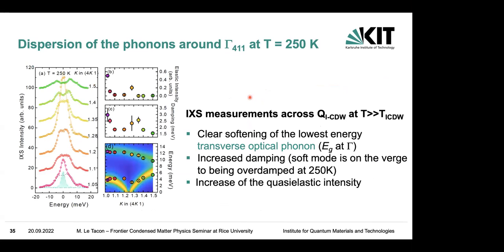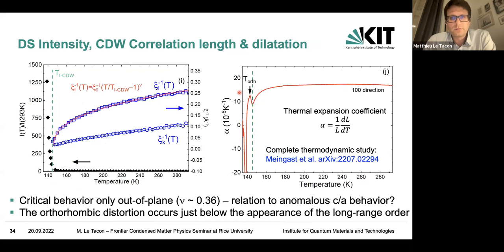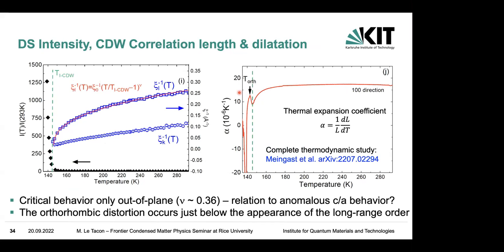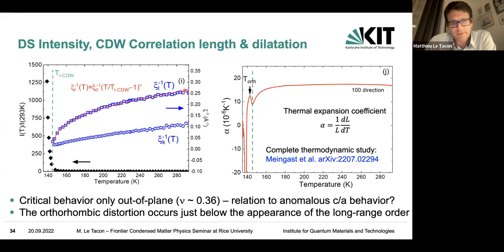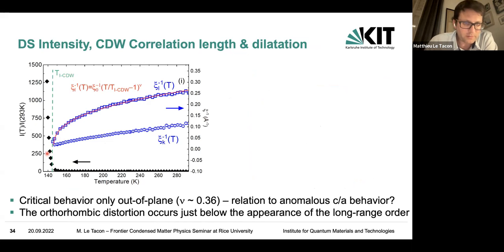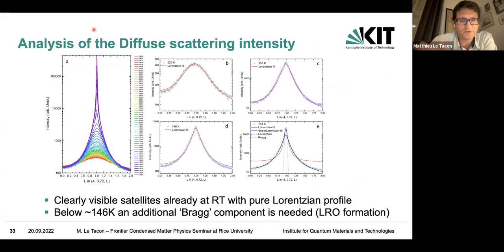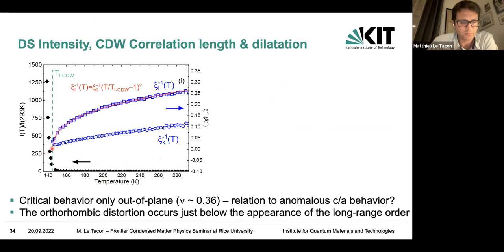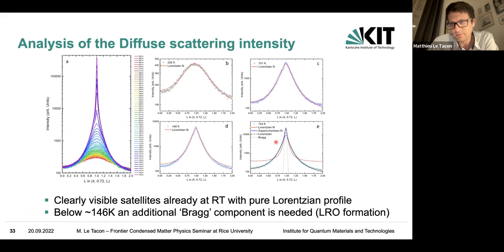Does it look like a first-order transition or second order? Second order. Okay. But your in-plane correlation does not diverge, right? I mean, it becomes kind of resolution limited. You just can't see it anymore. That's a good point. What I'm plotting here is really the fluctuation, the Lorentzian width of the fluctuation part. And then at that point, or below that temperature, what I do see is a resolution-limited Bragg reflection on top of the diffuse background, if you like.